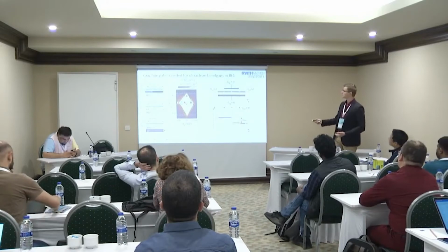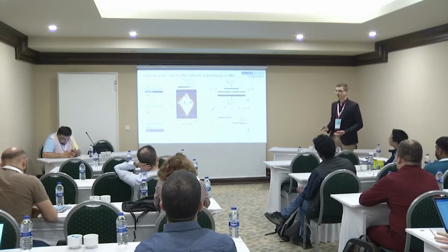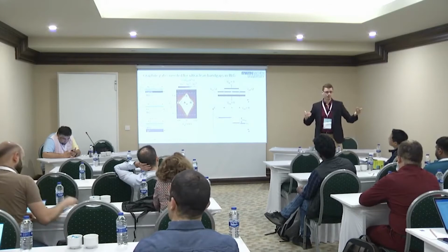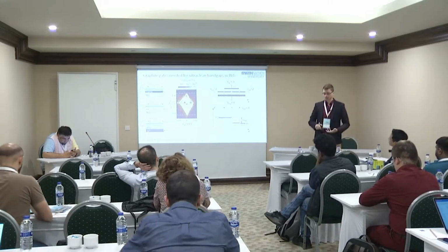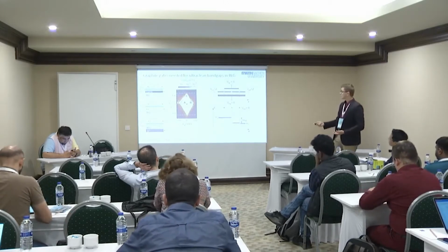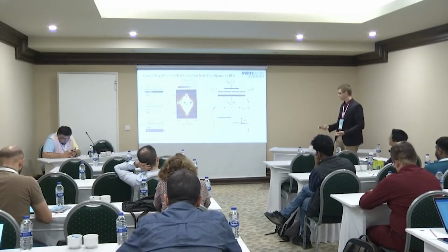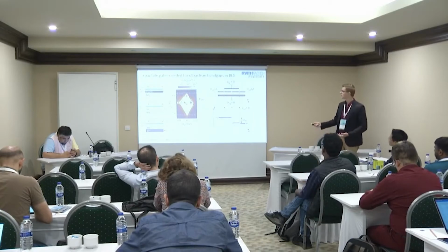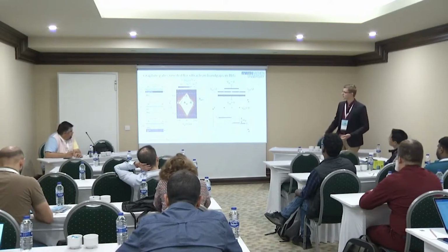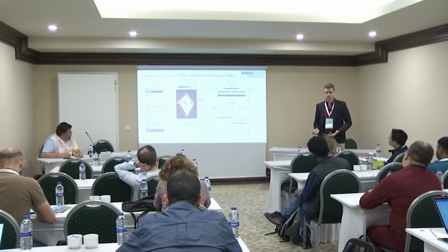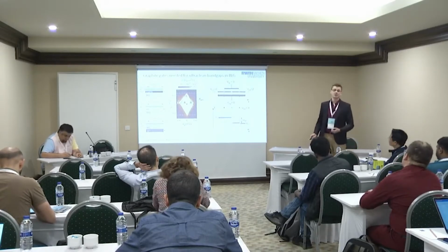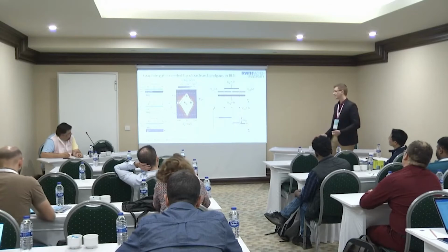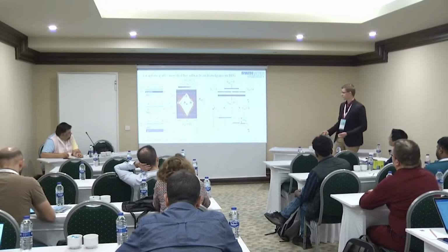If you start to increase the source-drain voltage until a point C, where the energy difference between source and drain becomes equal to the band gap we introduced with the displacement field, then current can start flowing again beyond this point C. This also means that we can directly extract the gap value from the difference of point A to point C on the y-axis. Now for graphite-gated bilayer graphene, we find this nice singular diamond shape here, showing great tuning of the Fermi level, and as the area inside of this diamond is very homogeneous, it also shows that the gap is very clean. How does it look for gold-gated bilayer graphene?